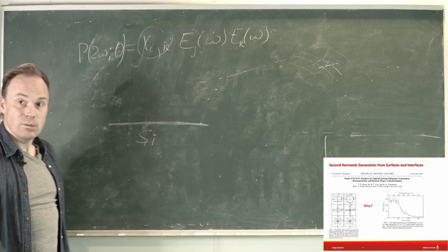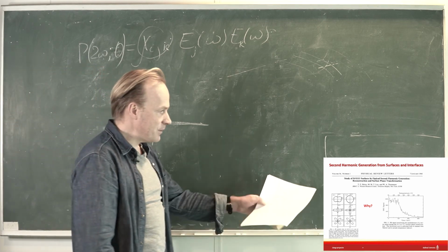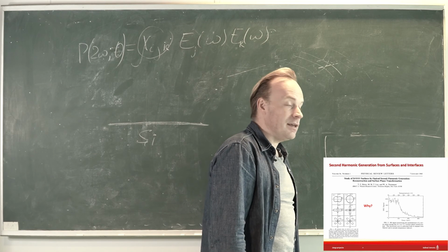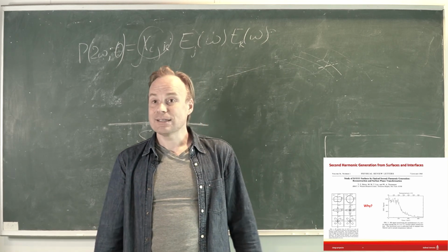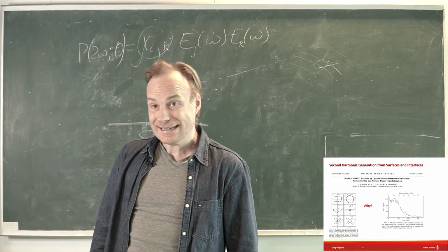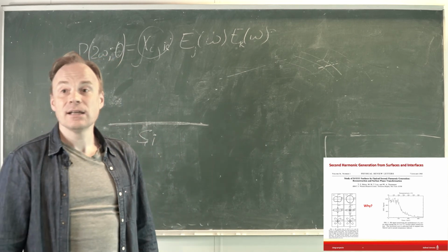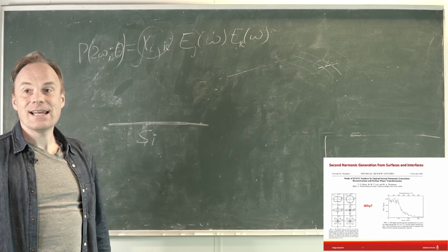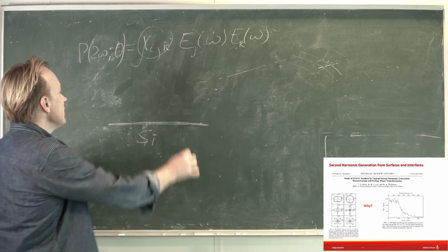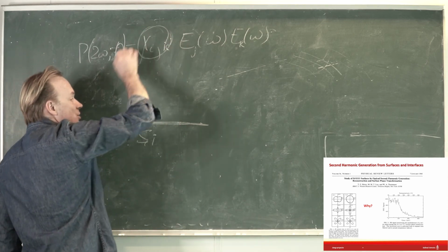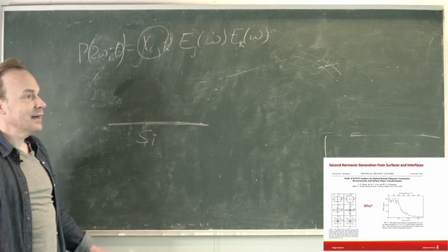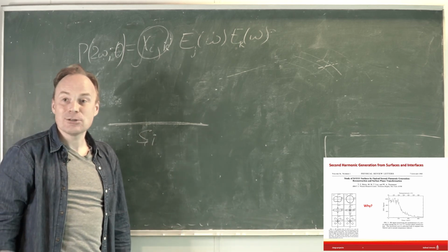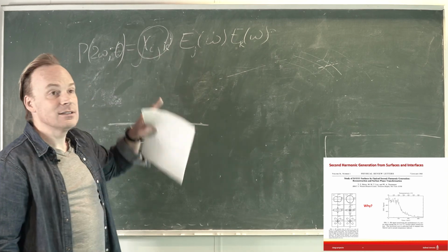And this trick was used in this paper shown on the slide, where they actually measured second harmonic generation from the surface of silicon, and more particularly using symmetry analysis of the tensor responsible for the second harmonic generation, they were able to find that the number of independent tensor components for this tensor is not that large.